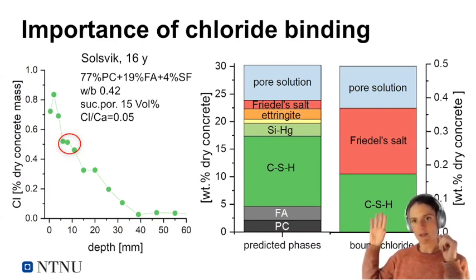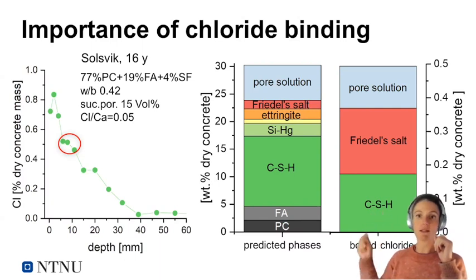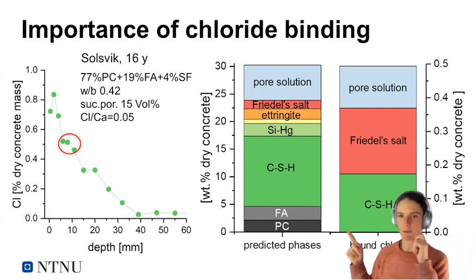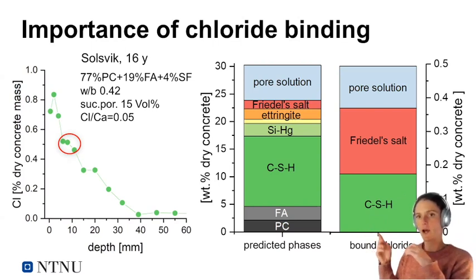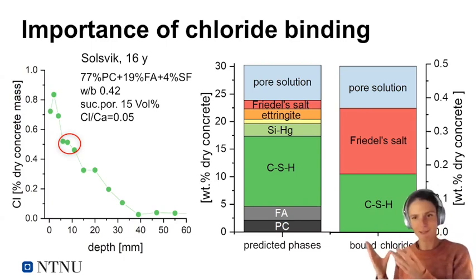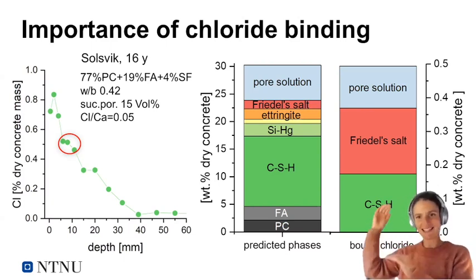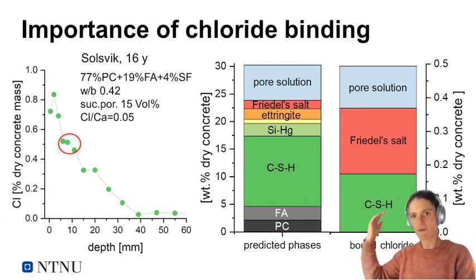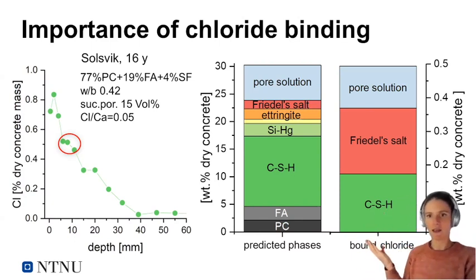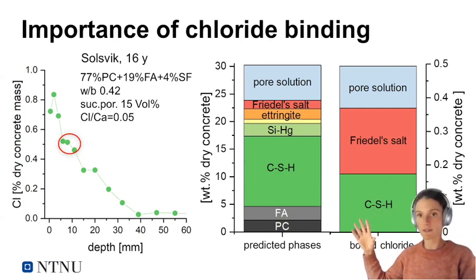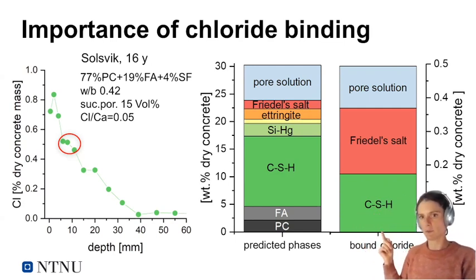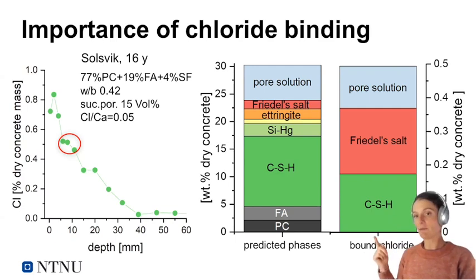And the remaining part I associate with the CSH. I determine the amount of CSH using thermodynamic modeling, and I also have some data from field exposed samples of how much chloride the CSH can actually contain. And this matches quite well. Though there are lots of assumptions here, so these levels can vary a bit, but it just illustrates. So if you look at a chloride profile, a large part of it is bound in either Friedel salt or adsorbed on CSH, and only a small part is free in your pore solution. So chloride binding is extremely important if you want to understand chloride profiles.